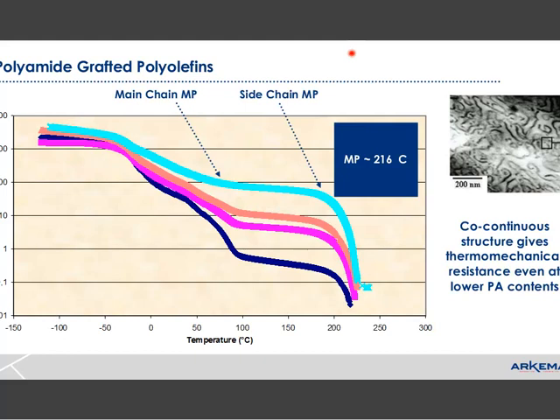What I have here is a DMA of different products with various levels of polyamide. Looking at the characteristic DMA, we have the softening of the polyolefin, which is occurring at these temperatures, and then we have the softening of the polyamide that's included in the structure. These different lines represent different levels of polyamide, where down here is a low level of polyamide and this is a high level of polyamide. And what we learn here is that the melting point is independent of the amount of polyamide, and that by raising the amount of polyamide you can get a product that maintains its structural properties over a very wide temperature range.